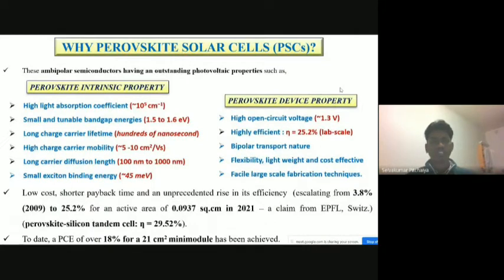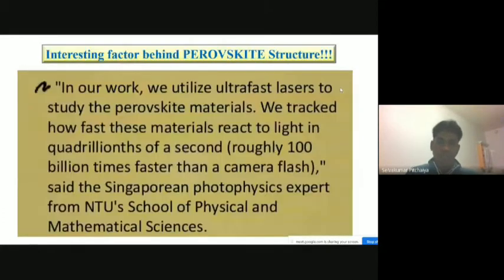Why is the perovskite solar cell particularly remarkable in third generation solar cells? Since it has tremendous intrinsic properties, outstanding properties within its material and also within the device as well. Nearly 30%, 29.52% efficiency has been reported so far utilizing this perovskite solar cell, and to date a 21 square centimeter mini module has achieved 18% efficiency. And I have told you that according to the International Energy Agency, 10% efficiency is enough to satisfy the world's total energy need. So we have almost reached double the requirement. So we are a step ahead to achieve good results.